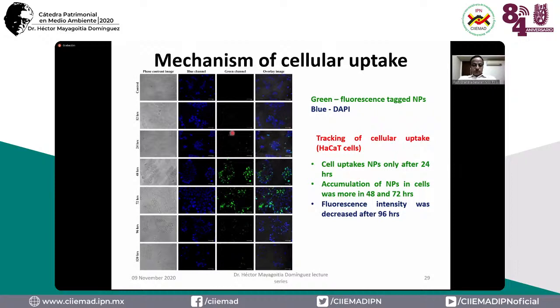And using fluorescent nanoplastics, we were able to see that the cells took up nanoplastics only after 24 hours. That means, what is happening before it? The cell was not able to recognize this as self or non-self. Only after corona formation, only after the protein is bound onto the nanoplastics, were the cells able to recognize that as a self material and engulf it.